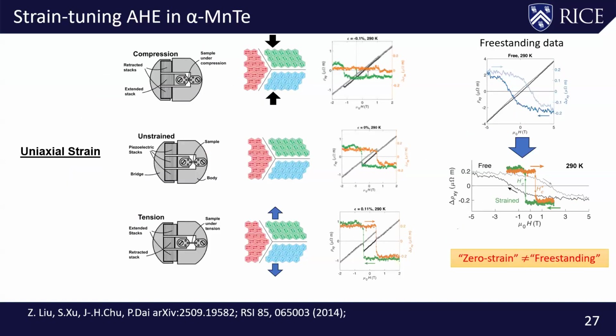And then we mounted the sample onto a piezoelectric system, and then started to measure the anomalous Hall effect. What we see immediately, it's actually transformative, is that in the case of zero strain, we see this hysteresis loop. But when you apply a strain to detwin the sample into a single magnetic domain, you see this hysteresis loop immediately become exceedingly sharp. And this is actually done on the same sample.